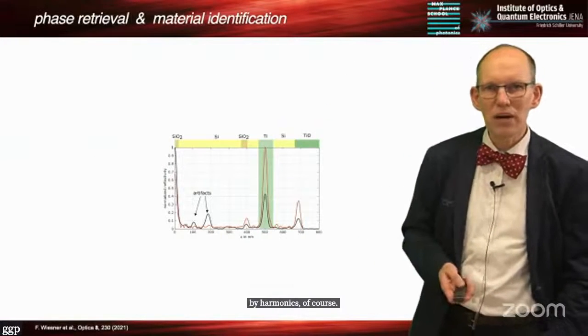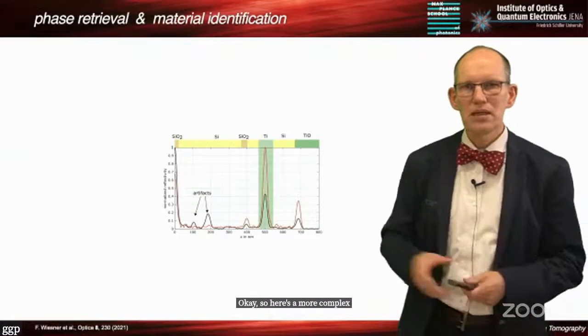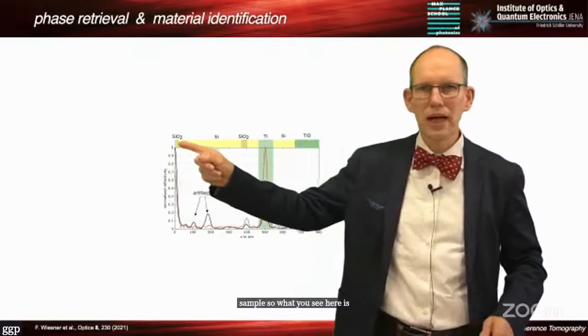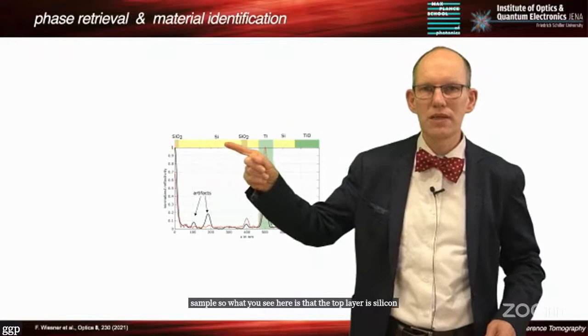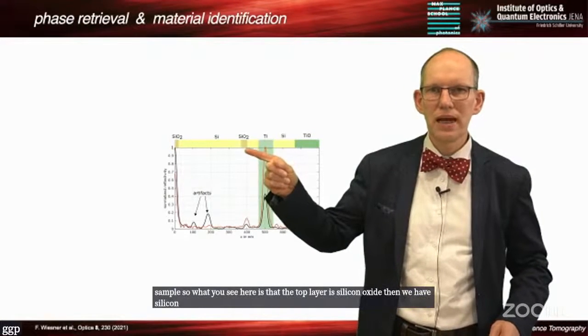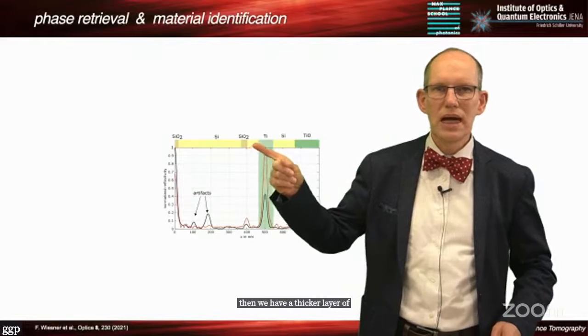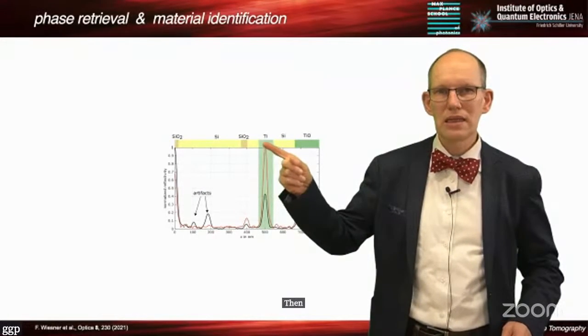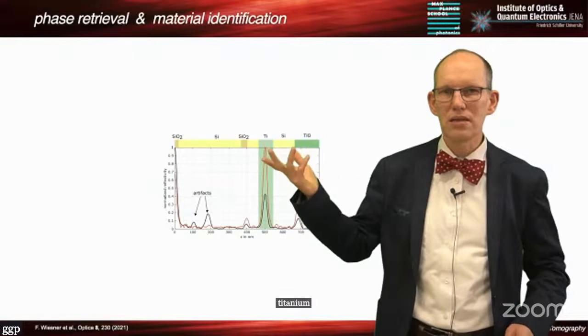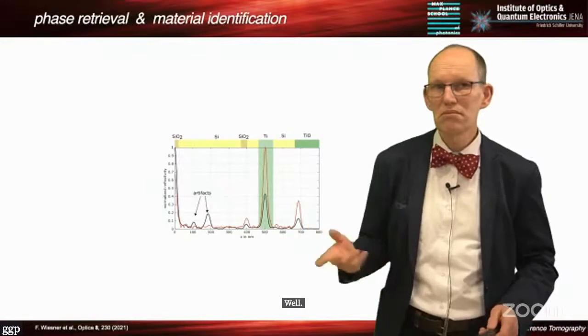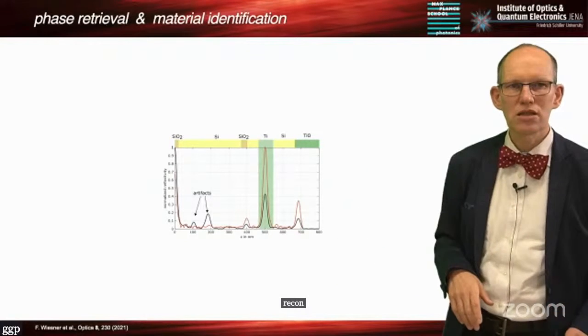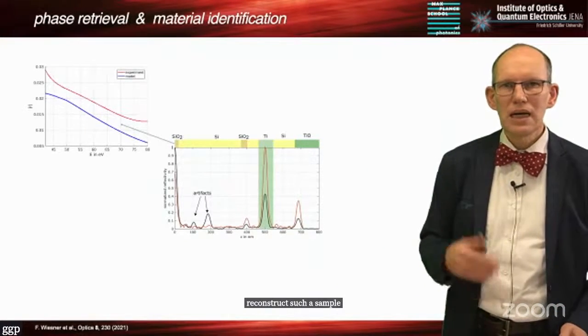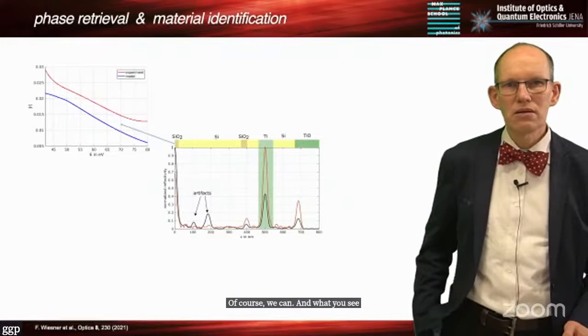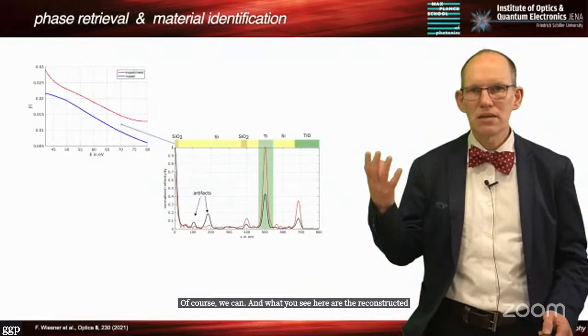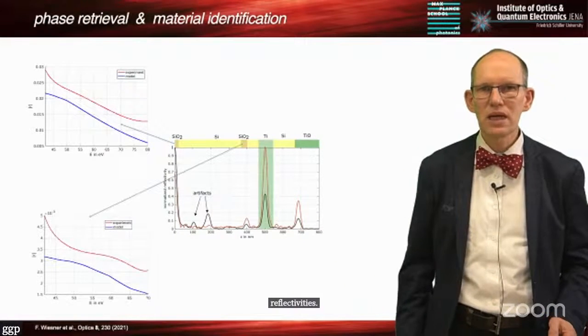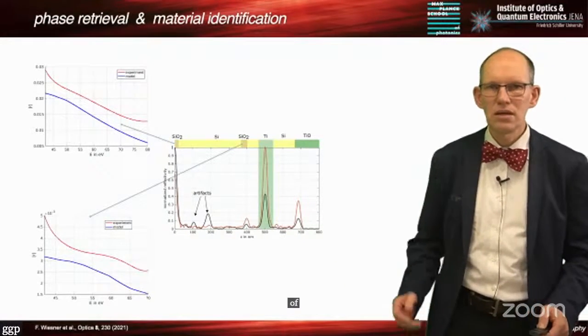Okay, so here's a more complex sample. What you see here is that the top layer is silicon oxide. Then we have silicon. Then we have a thicker layer of silicon dioxide. Then again silicon, titanium, silicon, titanium oxide. Question is, can we reconstruct such a sample? Of course we can. And what you see here are the reconstructed spectral reflectivities of the individual layers.